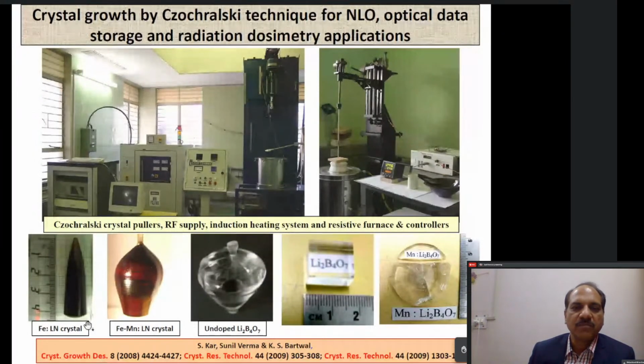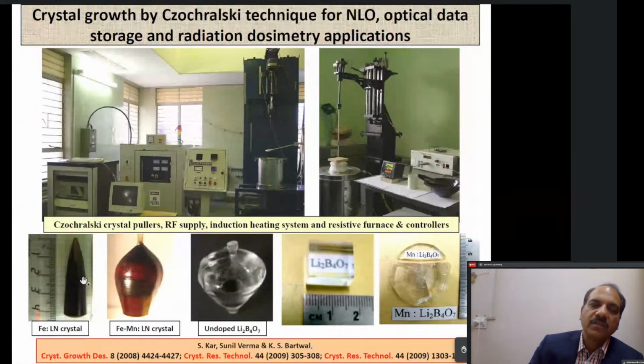So, and these are some of the crystals which we have grown. For example, we have lithium niobate, pure lithium niobate, then iron doped lithium niobate, manganese doped, undoped lithium tetraborate, doped lithium tetraborate, and the applications for which these crystals are grown are different. Right? For example, lithium niobate is a very good integrated optical material, it's an SHG material also, and it's a very good optical data storage material. So we use these materials for these applications.